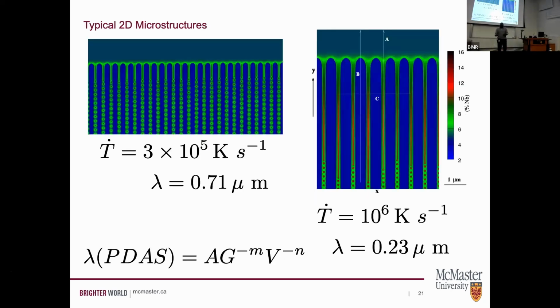So when you run one of these simulations, for this cooling rate, so the cooling rate in this case is just the gradient times the velocity of what that interface is moving like, we get these sort of microstructural patterns. So these are called cellular fingers. What you see here is concentration. So blue is low concentration. The red is high concentration. And what we've measured here is the spacing from tip to tip. That's a characteristic measure of microstructure when you see these sorts of patterns.